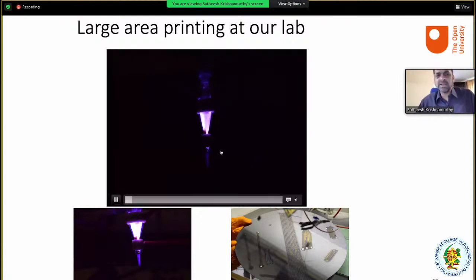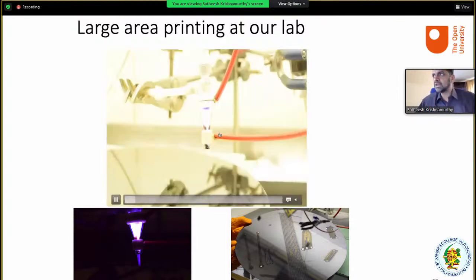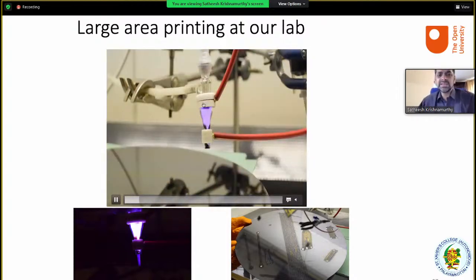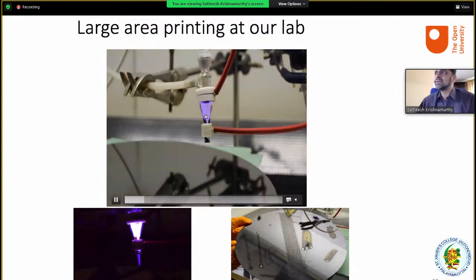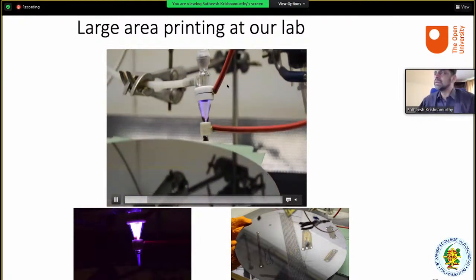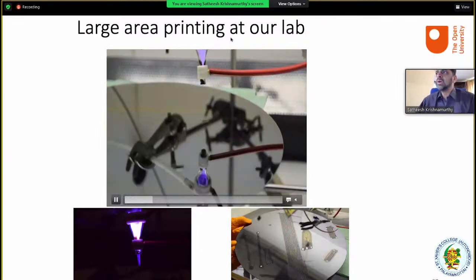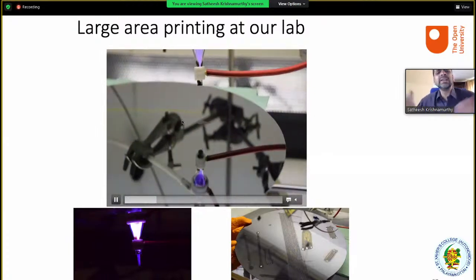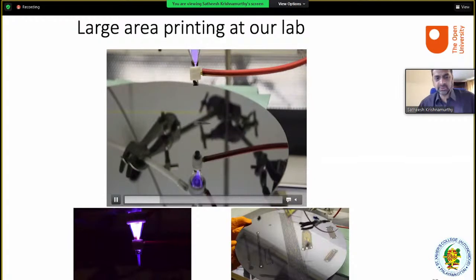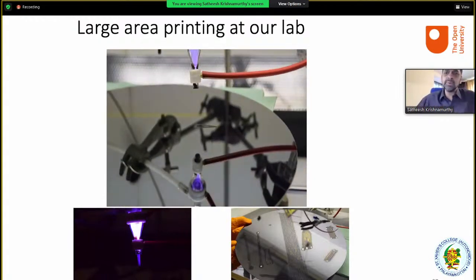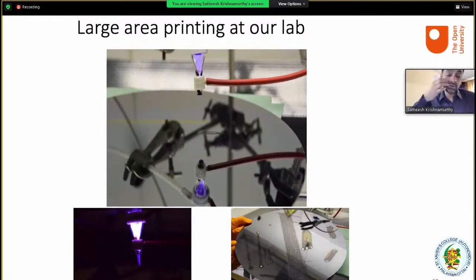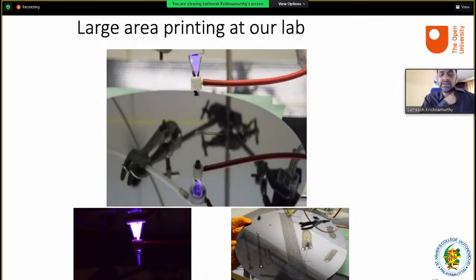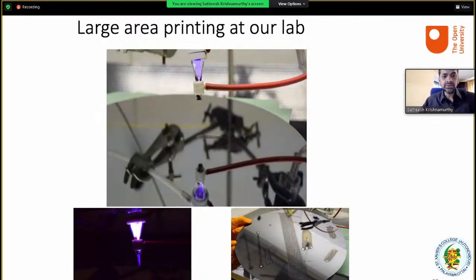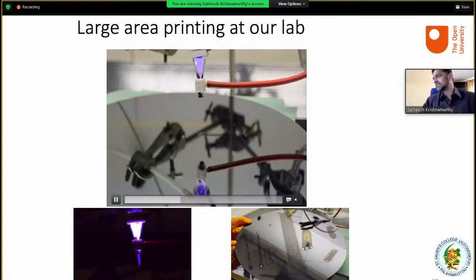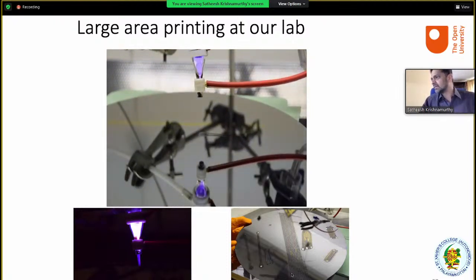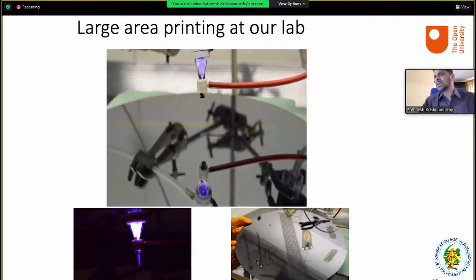So we scaled it up using our plasma printing methodology. As you can see, this is a homemade device. It's a cheap device. You can clearly see the plasma here. Plasma is ionized gas. We make some inks, and then the ink is directly deposited onto any wafers or any substrates. We can do that. So what we are showing is a homemade system where we were able to use an additive manufacturing tool. You can clearly see that we can draw lines, we can put contacts, etc. You can play with it.